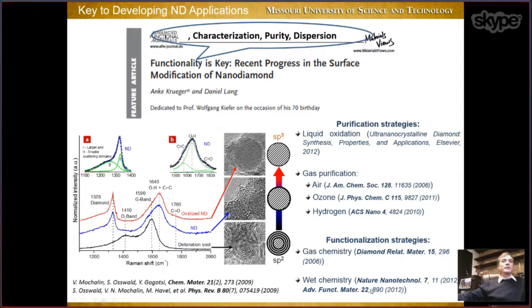So first of all, characterization. Whenever you get this material from the manufacturer, characterize it. You need to know what you work with. Then in most cases, purification is required. You need to remove all this non-diamond carbon, which you see here and here, graphitic shells. You need to remove all of this if you want to work with nanodiamond. And there are different purification strategies. Most common is liquid oxidation, which is used by manufacturers.